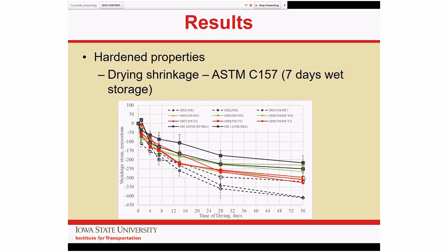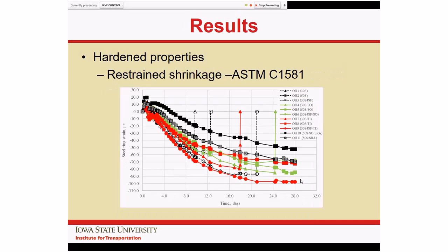The 50% slag mixtures are the green ones, and the 30% slag mixtures are the red ones. So again, we're balancing our desirability here. Again, the lower the shrinkage, the higher up we are on this chart, the better off we're going to be. And basically what we're doing is a trade-off game of what's good enough. There is no perfect answer.